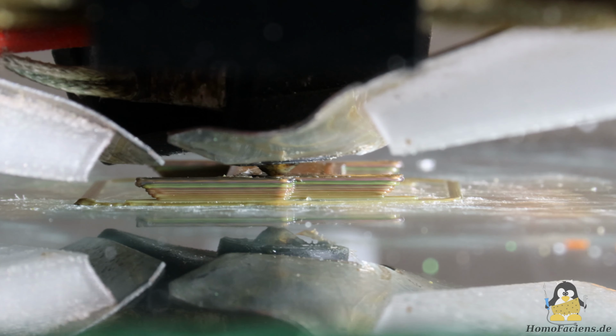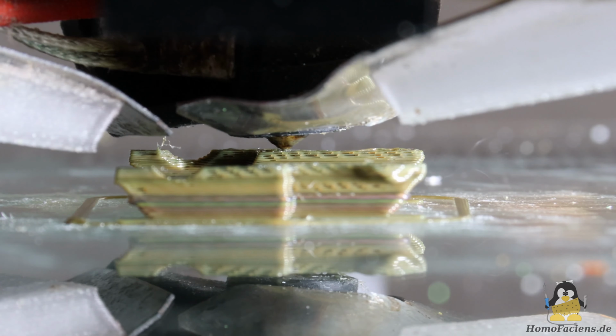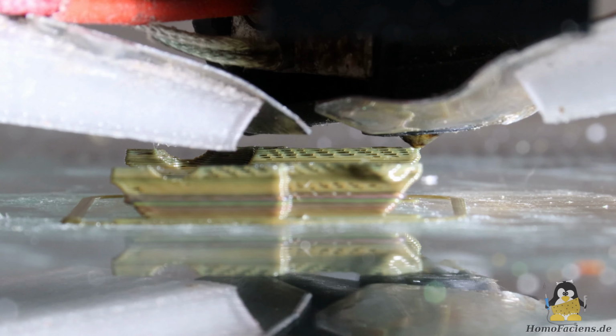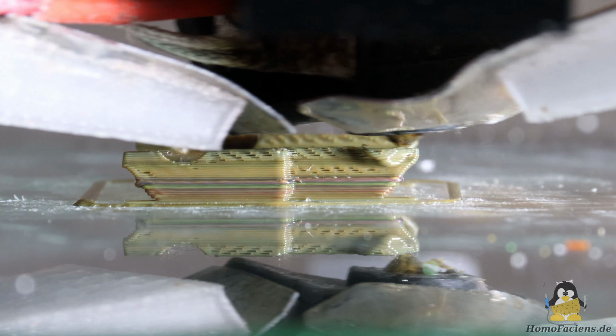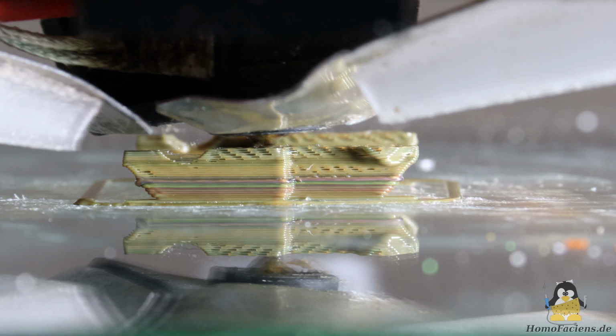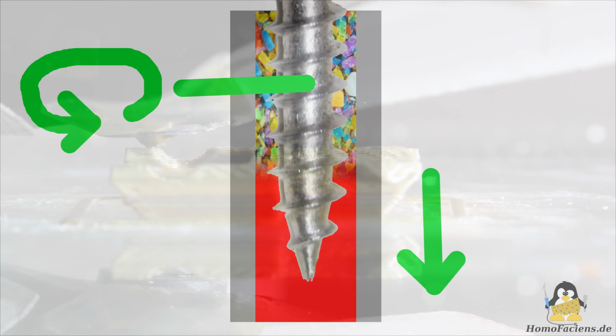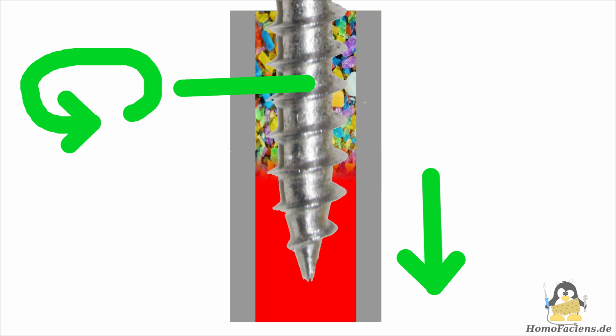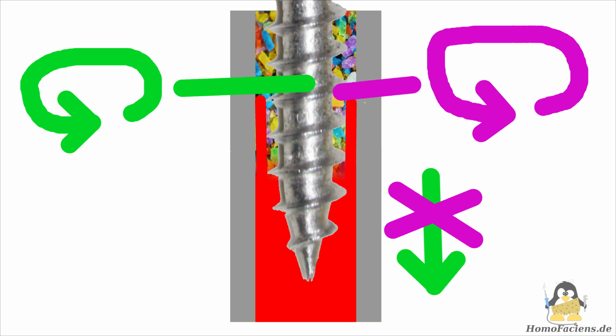Initially, the extrusion rate was nice and high, and the printing worked perfectly. But only after a few printed layers the extrusion rate dropped dramatically. The reason for this is that heat conduction along the tube causes the plastic to heat up through the extruder wall. This creates a lubricating film of liquid plastic in the transition zone. This in turn causes the plastic in this zone to rotate with the screw, which causes the extrusion rate to drop.